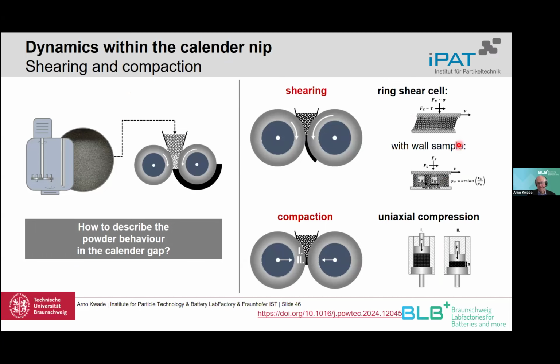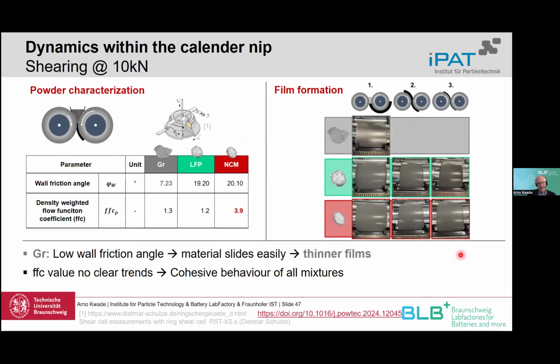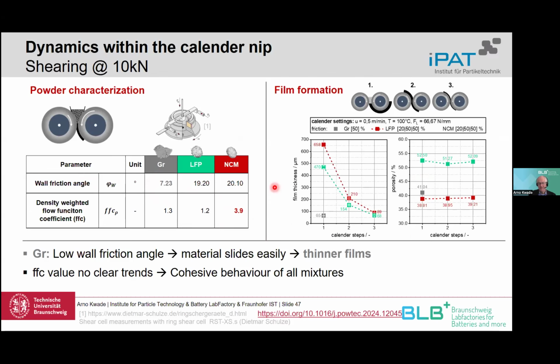That can be done by the powder flowability and also by the uniaxial compression. And you see that the powder flowability is different, especially the wall friction angle is much lower for the graphite, and that helps so that we only need one step to produce the electrode. With LFP and NCM, you see we have much higher wall friction angles, but there are some differences in the flowability, but that is not so decisive. But the wall friction angle is decisive, so that we need 3 steps here to get the right thickness of the electrode. Also, what can be seen here, here's 1 step, all is fine. Here we need 3 steps to come to a thickness below 100 micrometer.